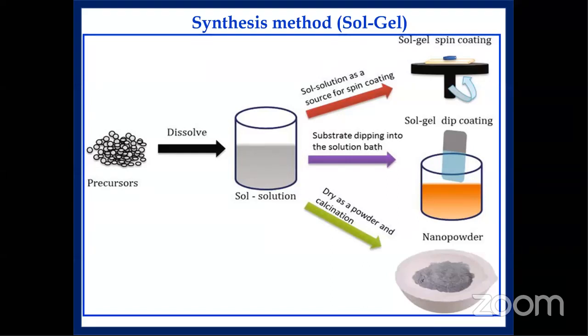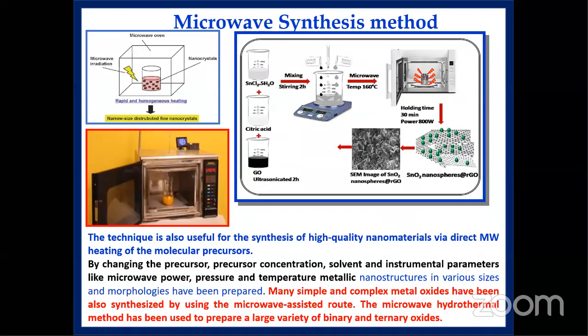Nanostructure thin film is prepared by this sol-gel dip coating method. And next is the microwave synthesis method. This technique is also useful for synthesis of high quality nanomaterials. We prepared tin oxide nanospheres decorated on graphene sheets. So we used graphene oxide, ultrasonicated for 2 hours, and then we added citric acid and then tin chloride hydrate. After mixing, the solution was stirred with the help of a magnetic stirrer. After getting a homogeneous solution, we kept it in the microwave oven.